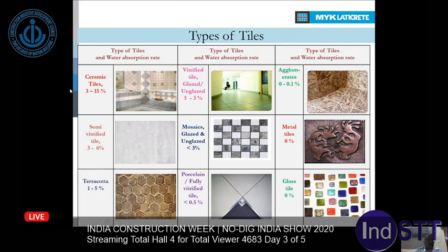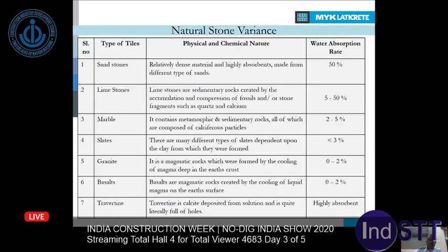If you look at here, the ceramic tile has 15% water absorption. Whereas porcelain or vitrified tile, which is most commonly used nowadays, is less than 0.5%. And even less with the metal tiles that are also fixed on the floors or in commercial areas, or glass tiles for aesthetics. They have no water absorption at all. Similarly, natural stones are another huge flooring or tiling category in India. Almost 50% of our construction or flooring is fixed with stones or marbles. And as you see from here, we have very varied water absorption. Go from sandstones to travertine or granite, and you can see the variations in the water absorption.